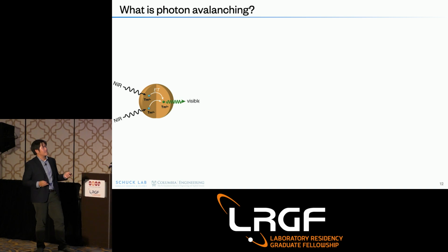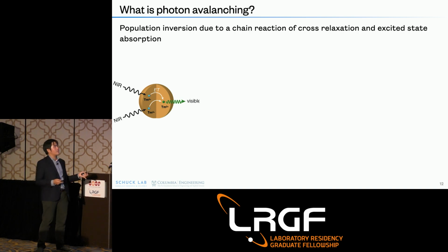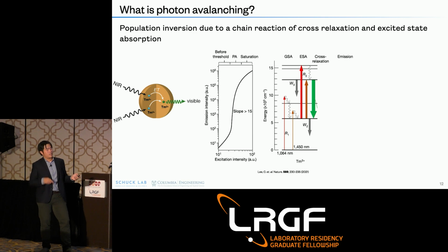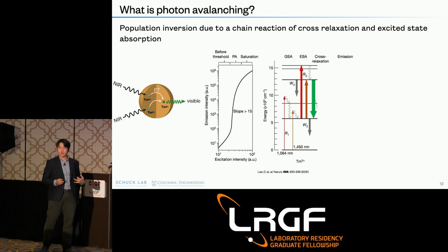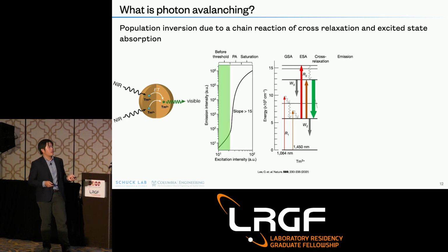So what exactly is photon avalanching? You're getting population inversion due to a chain reaction of cross-relaxation and excited state absorption processes that dominate in this nanoparticle. If you look at the signature of avalanching in this case, which is the high nonlinearity shown here, there are actually two other criteria, but I won't go into them further. What you have here is that when you start to excite the material, we chose a wavelength that is resonant with the first excited state transition and the second excited state transition, but the ground state to the first state is not resonant.